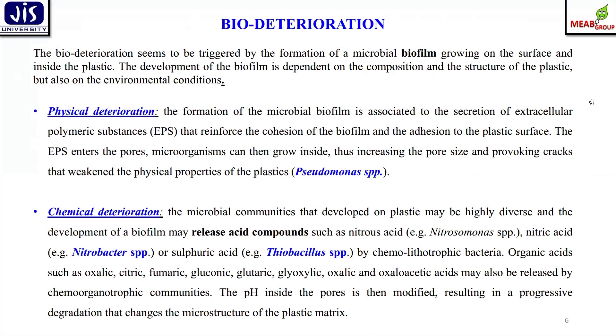The formation of microbial biofilm is associated with the secretion of extracellular polymeric substances, that is exopolysaccharides, which reinforce the cohesion of biofilm and adhesion to the plastic surface. The EPS enters the pores; microorganisms can then grow inside, enlarging pore size and provoking cracks that weaken the physical structure of the plastic. The most predominant microorganism involved in physical deterioration is Pseudomonas species. In chemical deterioration, the microbial community may release acid compounds such as nitrous acid by Nitrosomonas species, nitric acid by Nitrobacter species, or sulfuric acid by Thiobacillus species.